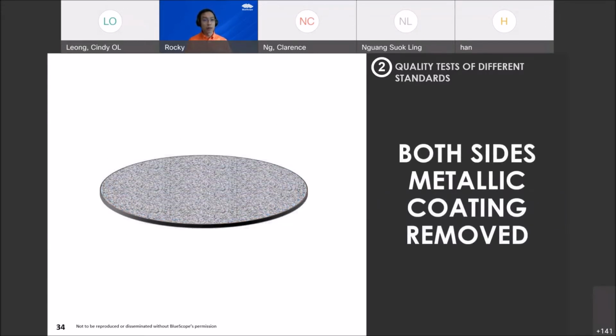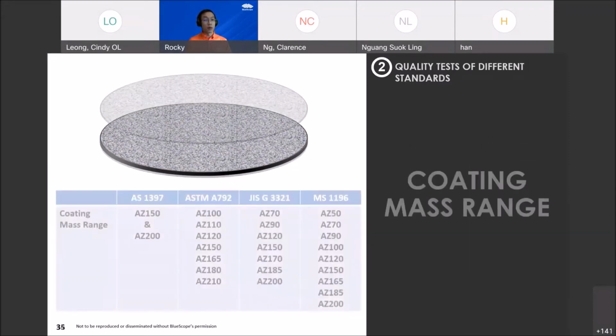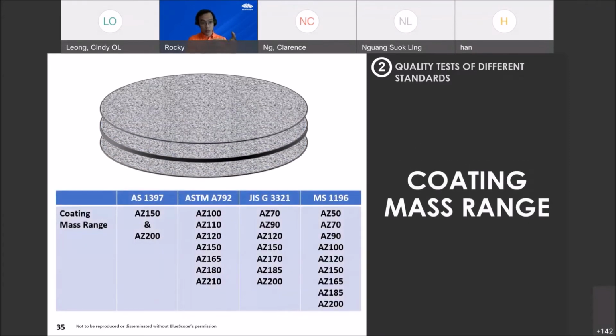And from there, we measure the weight of the one sample, with the metallic coating removed. Then we subtract that weight difference, which represents the weight of the coating, and divide it by the area. That gives us the coating mass in grams per meter square. Those are actually defined under the AZ number behind it, right?